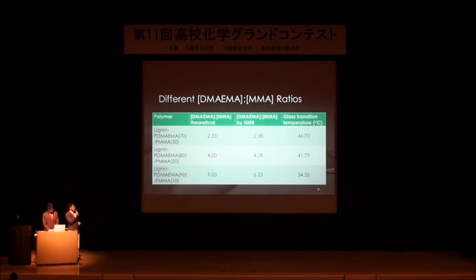We have determined the glass transition temperature of our 3 different polymers with different DMA to MMA ratios. So as you can see, when the DMA-EMA to MMA ratio increases down this table here, the glass transition temperature of our polymer decreases. So this tells us how we can control the hardness or softness of our polymer simply by varying the concentration of DMA-EMA, as well as MMA.